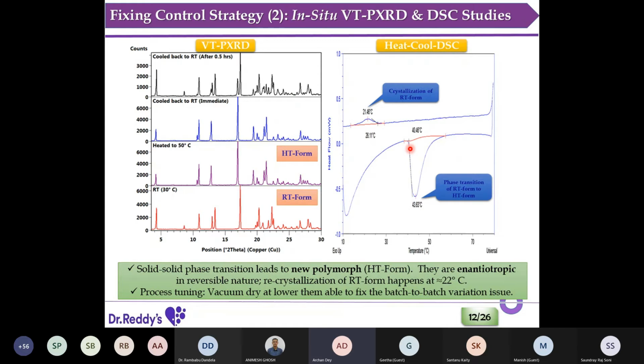And then we did a very simple heat-cool DSC study. What we can see is that around 43 degrees there is a phase transition, and when you cool it, this material crystallizes around 22 degrees. That's why in powder XRD we can't see it immediately, because our experiment is done at room temperature, but its crystallization temperature is below room temperature, around 20. But if you wait some time, it starts to enrich the RT form.